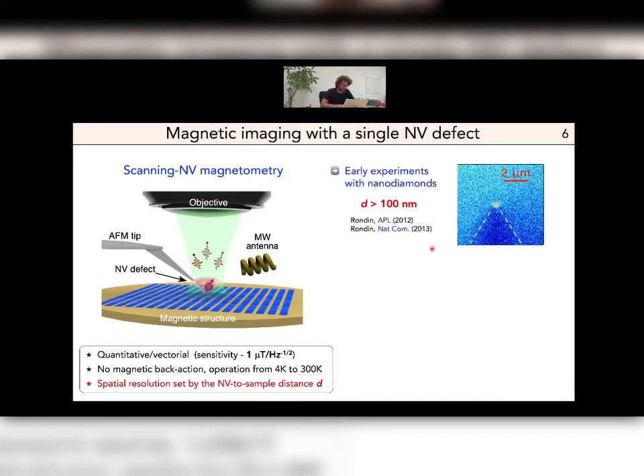So to engineer the sensor itself, there are two options. In early experiments, a solution was to graft small nanodiamonds, a few tens of nanometers in diameter, at the apex of the tip. The drawback of this technique is essentially that you can hardly reach a probe-to-sample distance better than 100 nanometers.